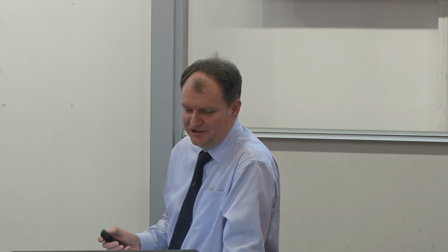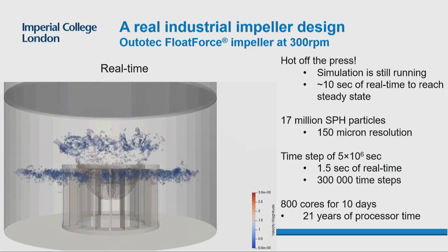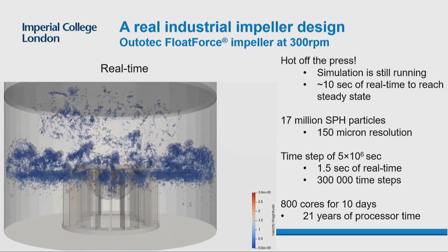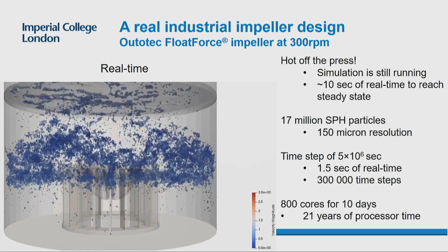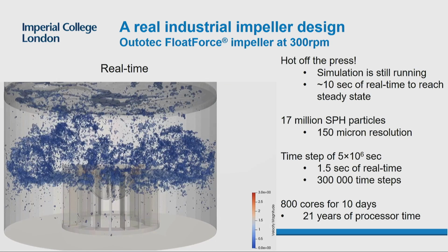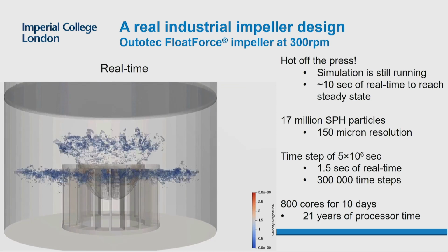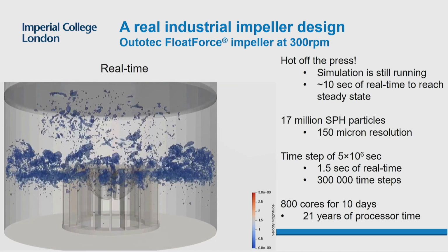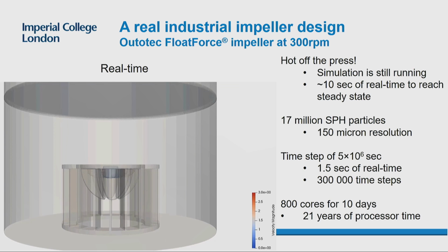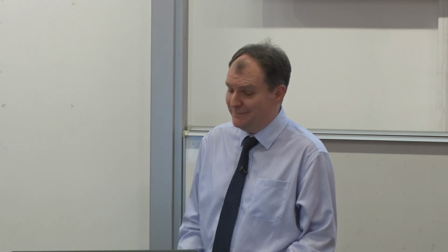very easily. The very latest simulations I'm doing are actually for a real cell, and these ones are somewhere towards the limit of what I can do. This is hot off the press, it's still running as we speak, and I'm trying to simulate bubble breakup in a real industrial cell. I've got about 17 million SPH particles that I'm simulating. I'm trying to get to 10 seconds or so, which is about how long a real cell takes to reach steady state. This is about 1.5 seconds in, which given the time step is about 300,000 time steps already.